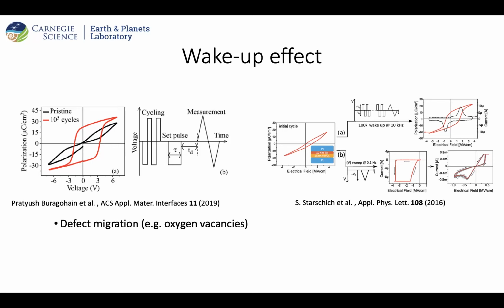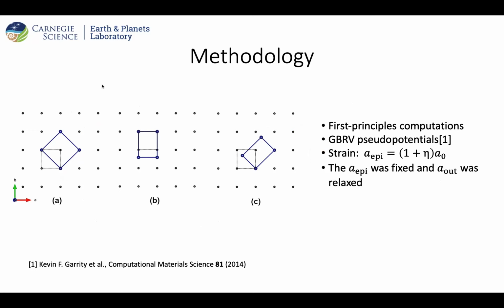Since we're talking about the orthorhombic phase, let me first start with how to lay out an orthorhombic unit cell epitaxially. We have three different kinds of scenarios: if the lattice constants are close enough, we can lay them on a square and apply a biaxial strain. Or if it is totally mismatched, we can consider two different cases, such as B and C, where either one of the short axes is in registry with one lattice constant, or the long axis is in the diagonal.